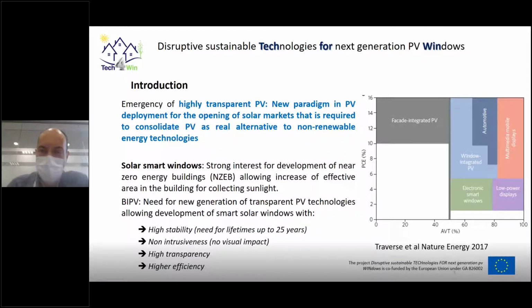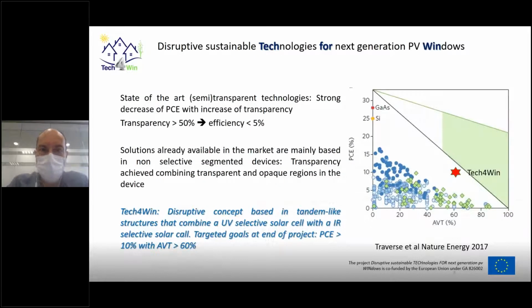Then we need, of course, a high level of transparency, higher than 50%, and we have to go to as much higher efficiencies as possible. So at this moment, there are semi-transparent technologies, and in the previous presentations, I think I've seen some examples of semi-transparent devices. As you can see here in the graph, the problem is that there is a strong decrease in the efficiency when you increase the transparency. So when you go to transparency levels higher than 50%, the efficiency at this moment drops down to 5%.